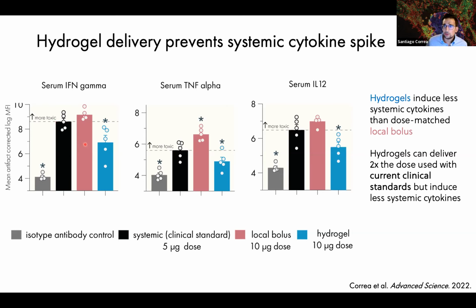Next up, we look at 2 different local regional drug delivery approaches, both administering twofold what we're administering in this black data. In red, we have the local bolus, and in blue, we have our hydrogel. And what you can see across the board is that the local bolus immediately starts increasing the pro-inflammatory cytokine levels in circulation, indicating that this treatment is more toxic. And some additional data on weight loss that we have bears that out. In contrast, our hydrogels are able to significantly attenuate these levels compared to the clinical standard approach, which is exciting, especially since we're delivering 2 times what we're delivering in this black data.